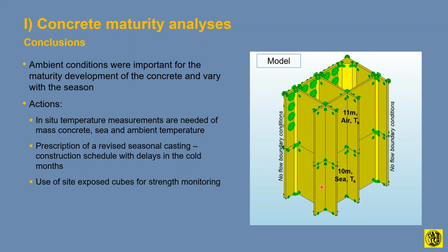We also recommended that they should record in situ temperatures, ambient sea, air, and concrete during delivery, for the entire length of the project. And also, what is the safest, of course, is to use cube specimens which we call site exposed, not standardized cubes which you send to the lab in order to break at 7, 14, or 28 days. But you leave them on the site. You can submerge them next to the sea, inside the sea, or you can leave them to be cured in the same conditions as the caisson above sea level, and you break them at 7 days so that you have the site strength. The site maturity of the concrete is a good index of how the concrete is behaving before starting the installation phase.